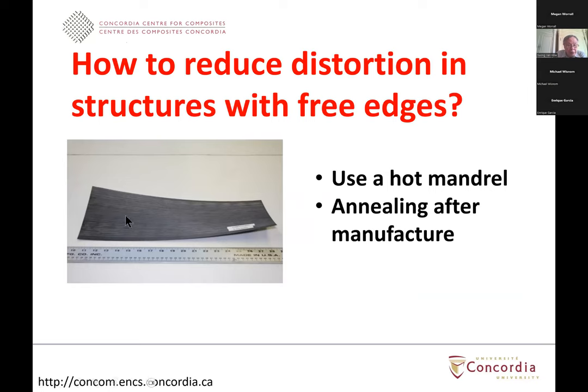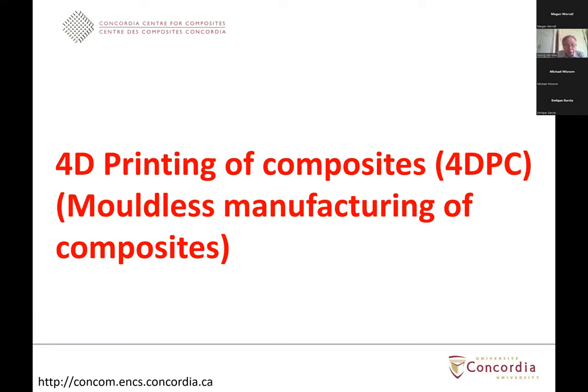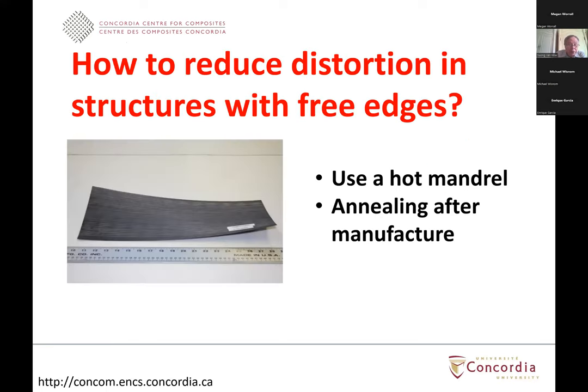But right after manufacturing, it gets to be distorted, and that means that you don't have anything like an unsymmetric laminate or anything like this. So this is an issue in terms of trying to make samples for the characterization. So what we have found is that if you use a hot mandrel, you can address this issue. And the other thing to do is to anneal the structure after you manufacture. You can also get rid of the distortion. So I think this one here summarizes some of the issues concerning automated composite manufacturing for thermoset and thermoplastic composite.